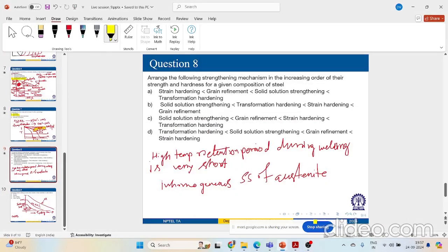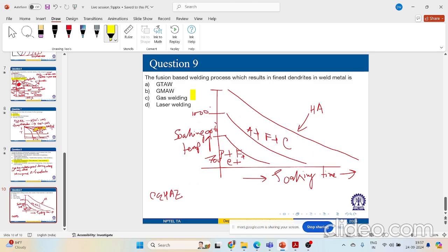I have to arrange the following strengthening mechanisms in the increasing order of their strength and hardness. So the maximum hardness will be for transformation hardening, then strain, then grain, then solid solution. So C is the correct option. Okay. And finally, the fusion based welding process which results in the finest dendrites in weld metal. Because gas tungsten, gas metal, gas welding will increase your heat input, the cooling rate will also decrease, right? So they will not form fine dendrites. They will form a coarse microstructure in comparison to laser welding. So laser welding will provide me the finest dendrites. Okay.